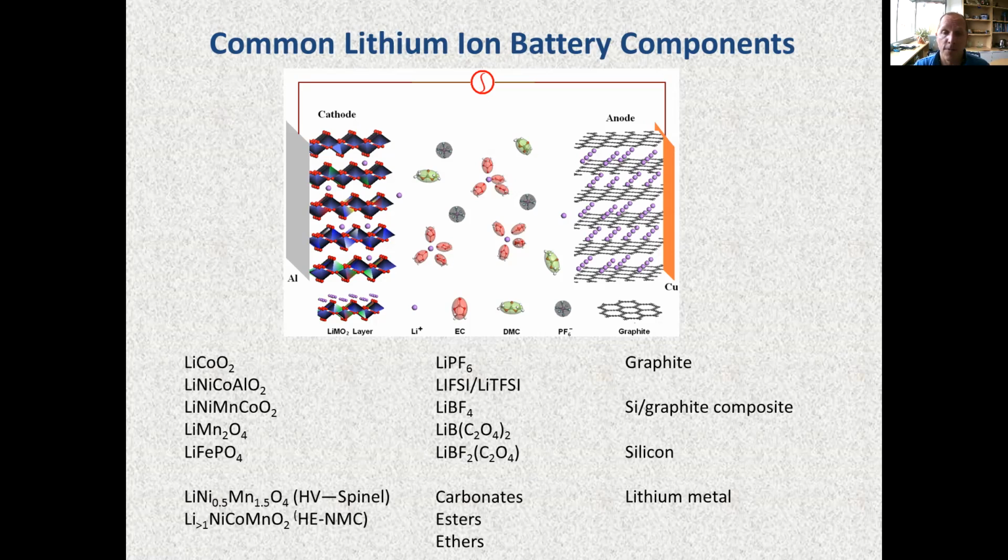So going back to the primary focus of this talk, which is the electrolyte. The electrolyte is a combination of a lithium salt, which is then dissolved in some solvents to make the electrolyte formulation. The most frequently used salts of interest include lithium hexafluorophosphate, LiPF6, which is the most widely utilized salt commercially for lithium-ion batteries. Two of the most recent lithium salts that have really become high interest to the battery community are LiFSI, which is lithium bis(fluorosulfonyl)imide, and LiTFSI, which is lithium bis(trifluoromethanesulfonyl)imide.